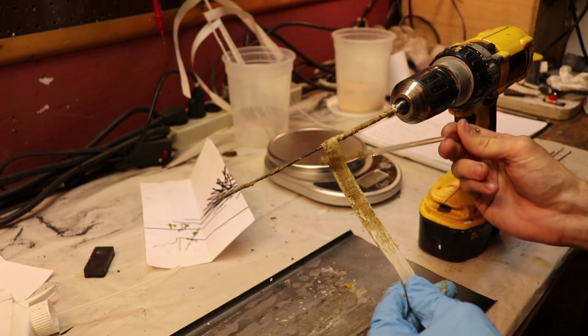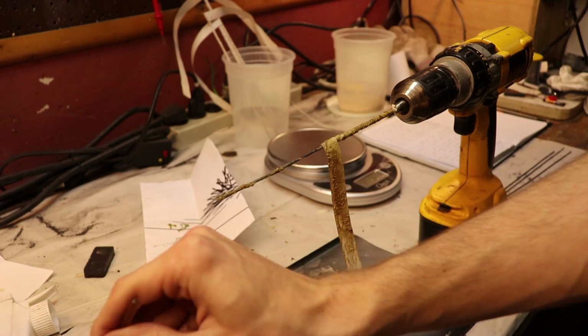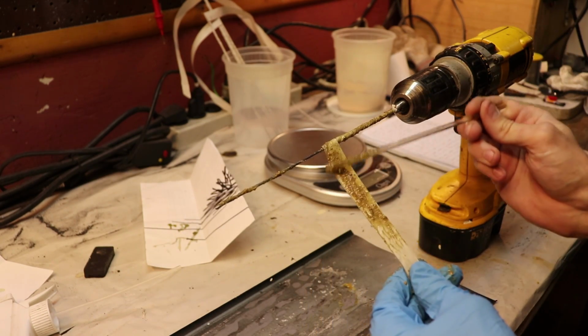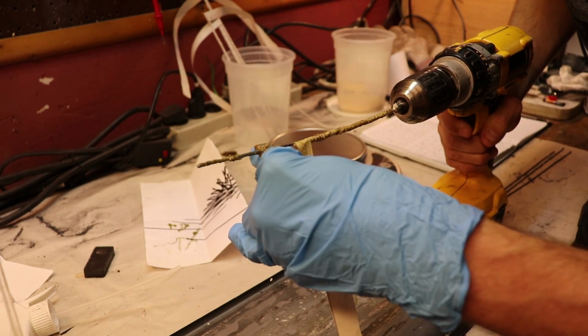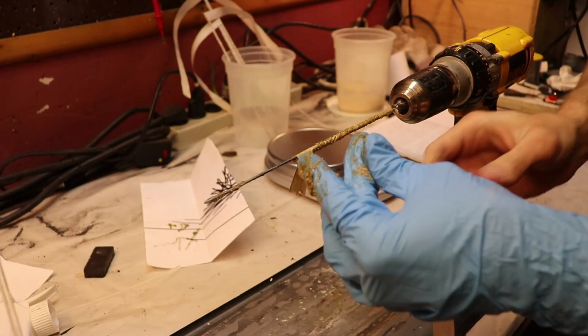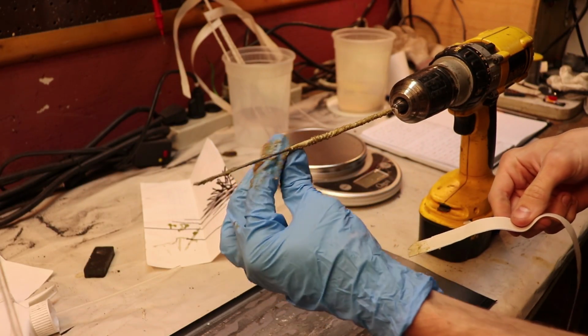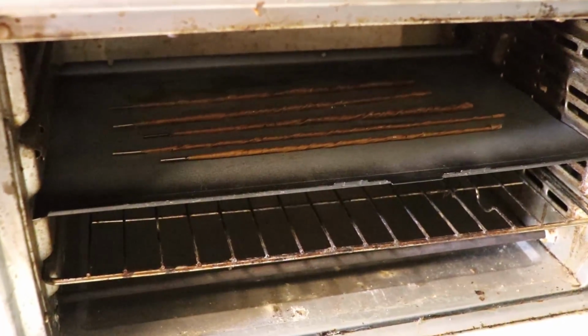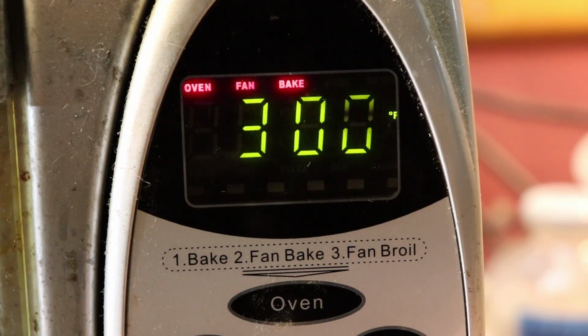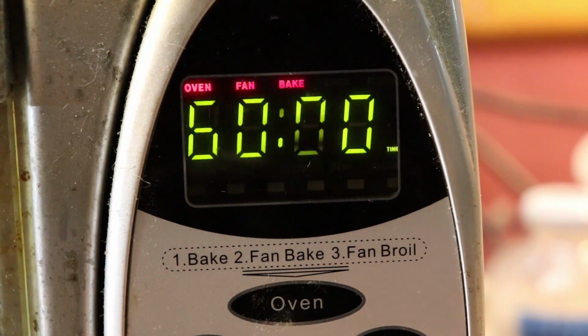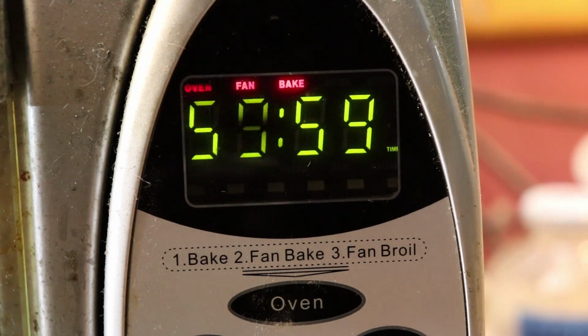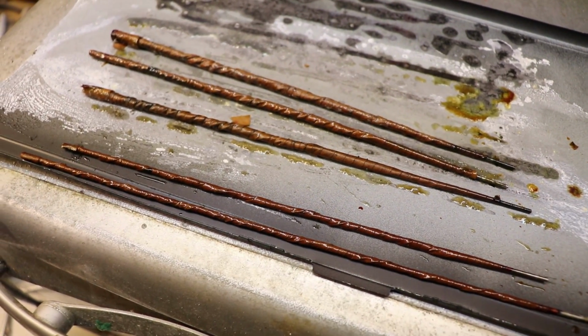I want to also add that I tried soaking the paper as I wrapped the rod, but once you wet the paper, it loses a lot of its strength and tearing is more likely to occur, so I don't recommend this method. I then put the rods in the oven, set the temperature at 300 degrees Fahrenheit, and let it bake for 1 hour. After the rods were dry, they were ready to weld.